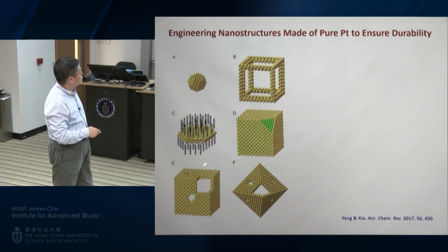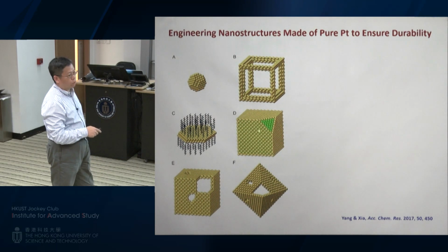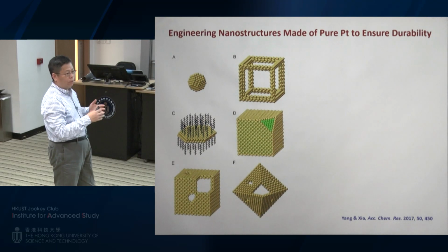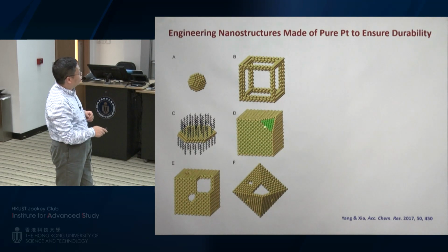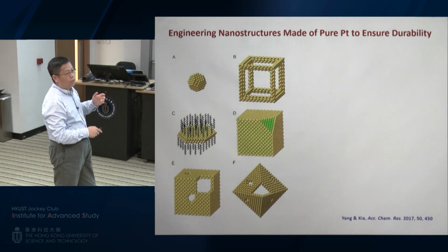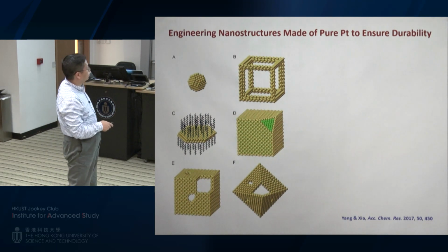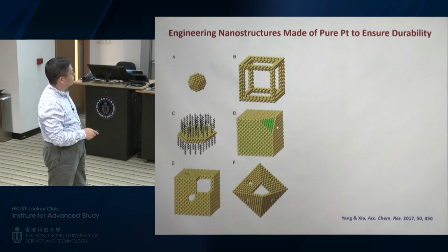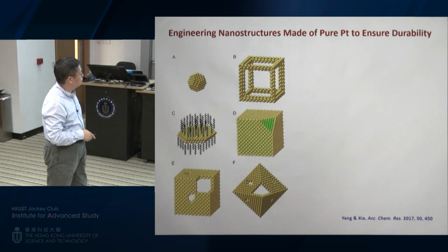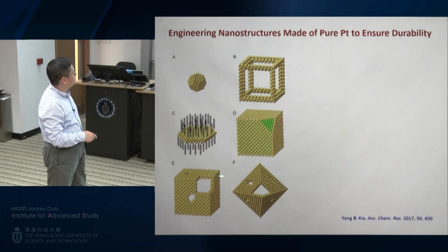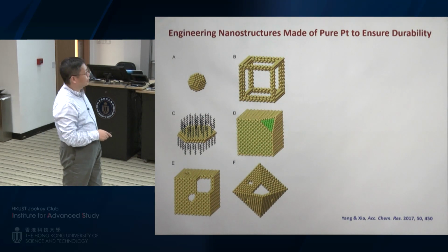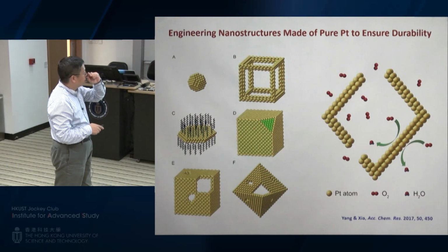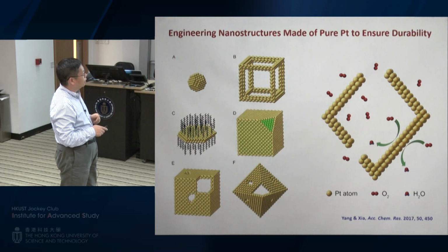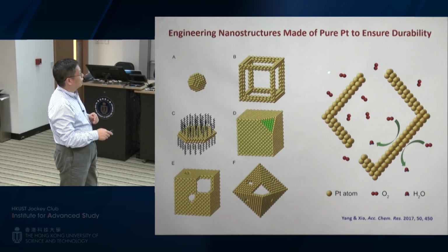And here is the approach we look at. One is to make a core-shell structure. I already showed you how to make palladium-platinum core-shell structures. In that case, the shell could be controlled at maybe 2 atomic layers thick or 3 atomic layers thick. So basically, it can increase the dispersion of platinum atoms or the utilization efficiency of the platinum atoms. Or you can etch away the palladium eventually to make these hollow structures. We call these nanocage structures. And if you can control the wall as thin as a few atomic layers, we believe this can give us a good catalyst to use.